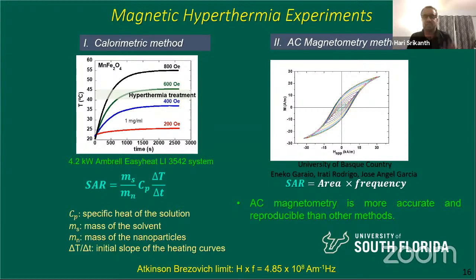So we have to make sure that since we are subjecting the patient to extreme conditions of high frequency and high amplitude AC, we cannot just arbitrarily apply any field at any frequency. Because if we do that, then you have the risk of nervous stimulation, okay? Nerve stimulations, it can lead to stroke. So essentially, you have to be very careful about the choice. So that's why we have to work with low fields and low frequency to the extent possible. We cannot increase to Tesla fields to gigahertz frequencies at these amplitudes, okay?